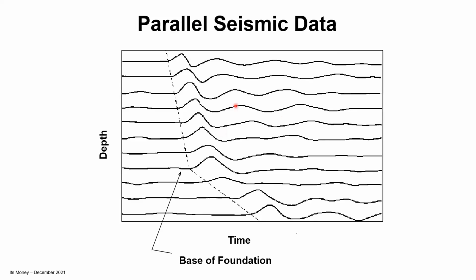The data is stacked for each hammer blow. We stack the data in this form. So there's the point of transmission, the impact, there's the point of reception. So again, we're measuring the time. As each blow is stacked, that time increases as we travel down the foundation in a uniform manner until we get past the bottom of the foundation where the signal is now traveling through more soil. And so the time increases. And it's this inflection point that tells us roughly where the base of the foundation is.